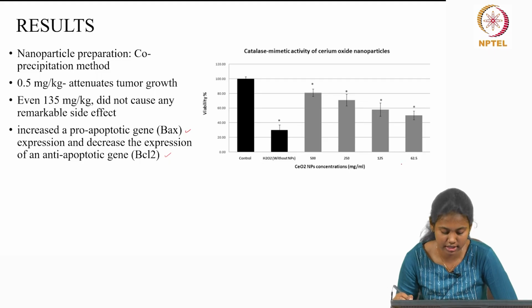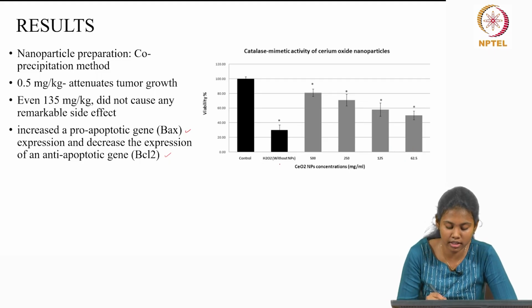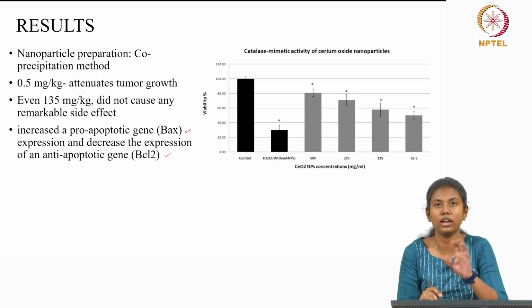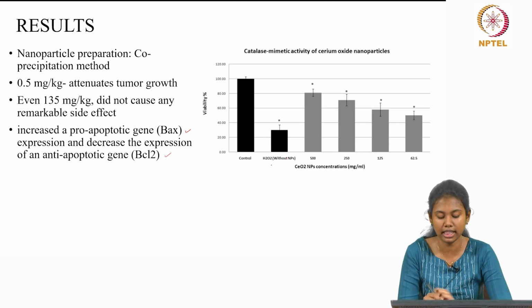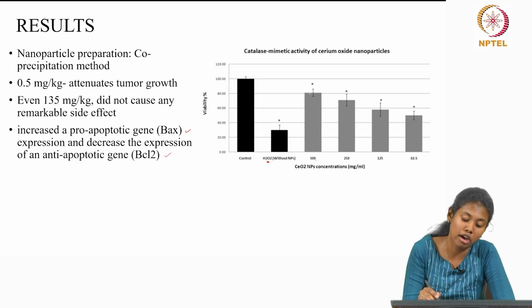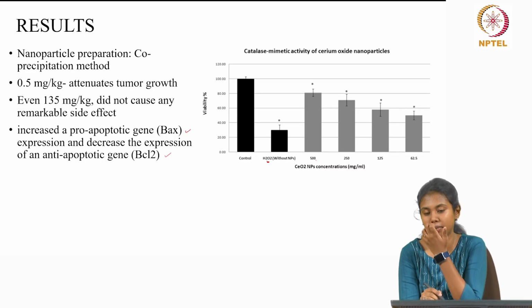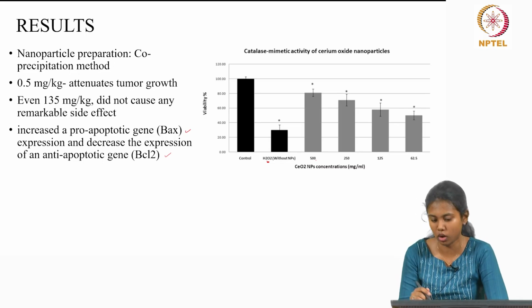Also, the antioxidant activity was studied, where they gave cells oxidative stress with H2O2. The cells treated with cerium oxide nanoparticles showed high viability, whereas the viability of cells without nanoparticles was very low. From this we can estimate that it has antioxidant potential in a normal cell as well.